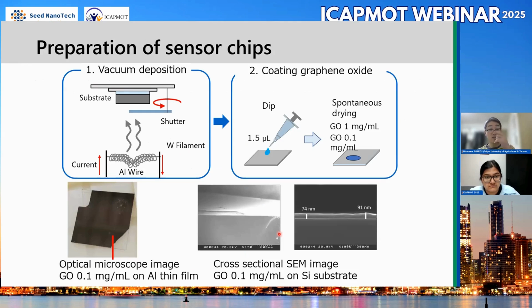So this is the schematic image of the preparation of the sensor chip. First, we deposited the aluminum on a glass substrate by using vacuum deposition. And then we coated the graphene oxide by dipping in the graphene oxide solution and spontaneous drying of the surface. This picture is an optical image of graphene oxide of concentration 0.1 milligram per milliliter on aluminum thin film. And the right figure shows the cross-sectional SEM image of graphene oxide of 0.1 milligram per milliliter on a silicon substrate. The thickness of deposited graphene oxide is about 70 to 90 nanometers.